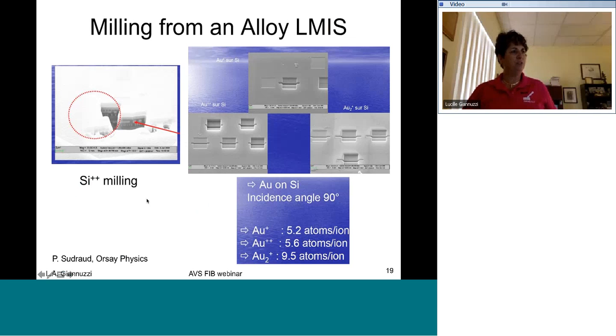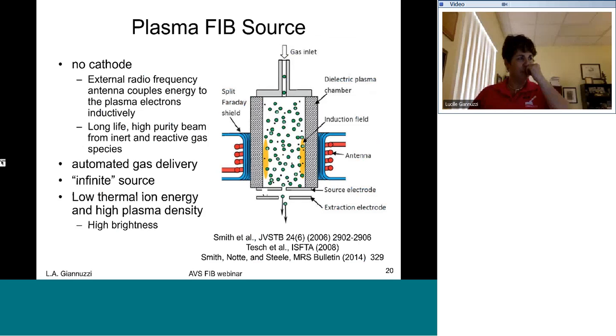So it's also possible, as I mentioned, to use a liquid metal alloy ion source. Sorry. So here, for example, we can use silicon plus plus, or we can use gold plus plus, or gold 2 plus. And because these masses differ, this also corresponds to a different amount of sputter yield, where the sputter yield is atoms per ion. Okay, but perfectly possible to do that. So you might want to, for example, use a particular source if you're looking at different materials. Okay. All right,